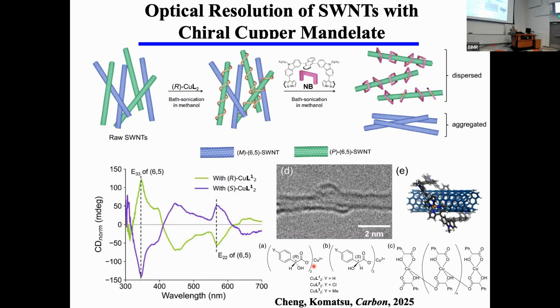And the copper mandelate actually forms supramolecular polymers like this. And of course, we can easily buy the R structure and the S structure of the copper mandelate. And when we apply the R structure or the S structure of the copper mandelate, it can discriminate the left-handed and the right-handed structure of the carbon nanotube, forming the complex like this. And when we apply this nano bracket afterwards to the metal salt, it can selectively interlock the carbon nanotube that forms the complex with the copper mandelate.